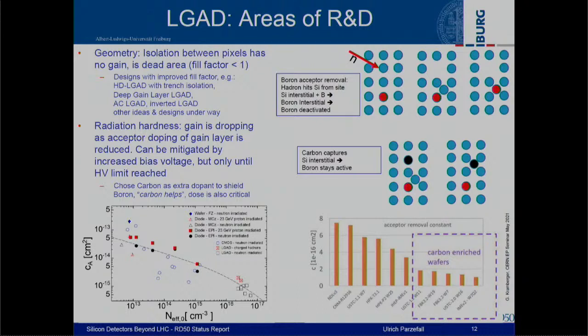The same happens in LGADs, and you can mitigate this radiation-induced performance degradation for a while by increasing the bias voltage, but only up to a certain point. Current research shows that co-implantation with carbon helps improve detector performance here.